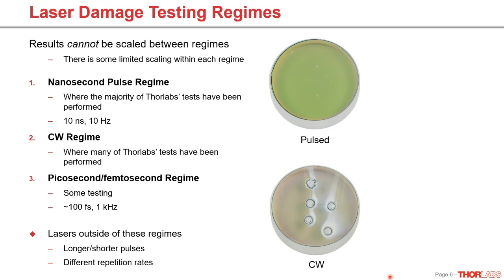So the majority of our tests have been performed in the nanosecond regime, and that's with 10 nanosecond pulses and at 10 hertz. We've done some percentage of our testing in the CW regime because we do have demand there. And we've done a small amount of testing in the ultra-fast picosecond and femtosecond regime. And that's typically with about 100 femtosecond pulses and at about 1 kilohertz. Obviously, there are lasers outside of these regimes, but we find that for most of our customers, they're working in one of these three.